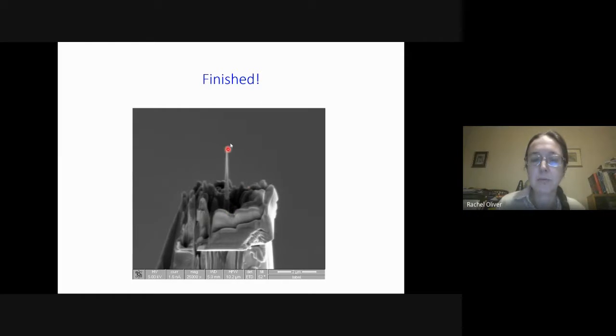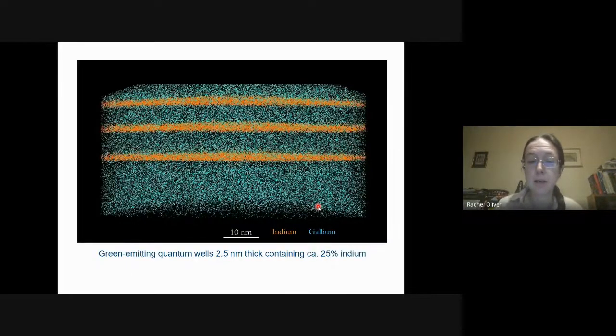Then this is one of our very first working atom probe samples with our steel needle and this very, very thin spike of gallium nitride sticking up from it. And this is one of our early atom probe data sets. So what we can see here, this is again a two-dimensional render of a three-dimensional data set. It's indium gallium nitride quantum wells with gallium nitride barriers. I'm not showing the nitrogen at all. I'm showing all of the indium atoms as little tiny orange dots, and I'm showing 25% here of the gallium atoms as turquoise dots.